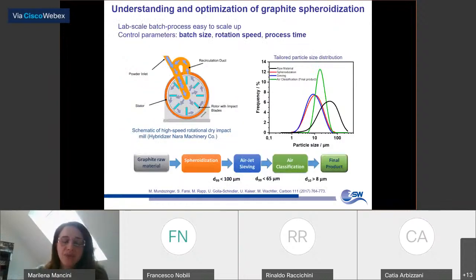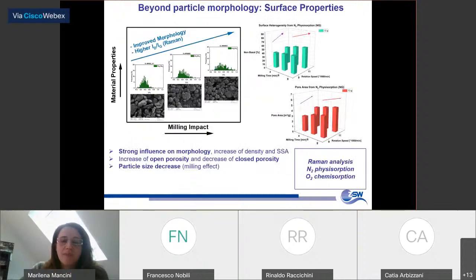What we have done during the past few years at ZSW is to use a lab-scale process for spheroidizing the raw material and then tailor the final particle size distribution to a very narrow range, to be able to use this material in lithium-ion battery anodes. Unfortunately, there is no time to go too much into detail, but what we have investigated very carefully is the effect of changing the milling parameters, not only on the morphology, but also on the particle surface.